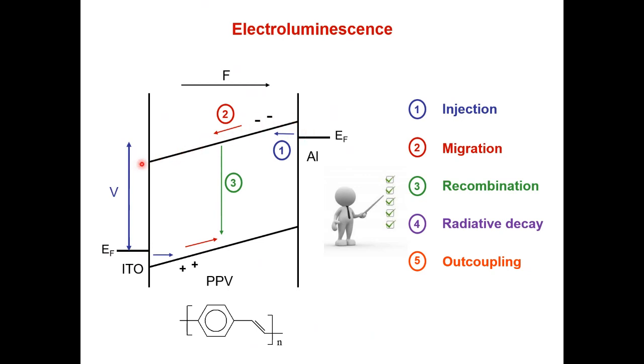Now, thanks to this kind of toboggan, you can inject electrons from this contact, and the electrons are going to migrate down the hill. You can remove electrons and create a hole here, and they are going to migrate under the influence of the electric field. So we talk about injection, migration, and at one stage, the hole and the electron will be on the same chain, and the electron in the conduction band here will be happy to go down to the empty place here, to the hole, and the extra energy will be released, hopefully by emitting some light, but also possibly by emitting some heat, which is not wanted in the device. So you need to have recombination and a radiative decay. This is what we are looking for.